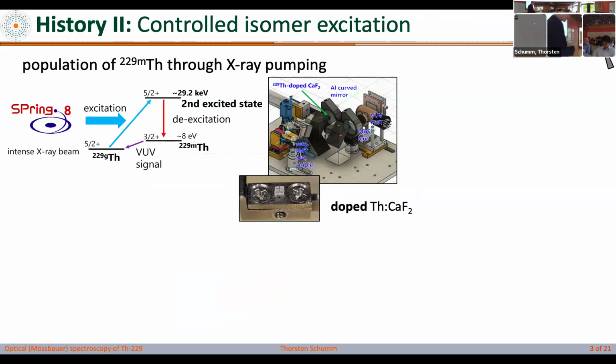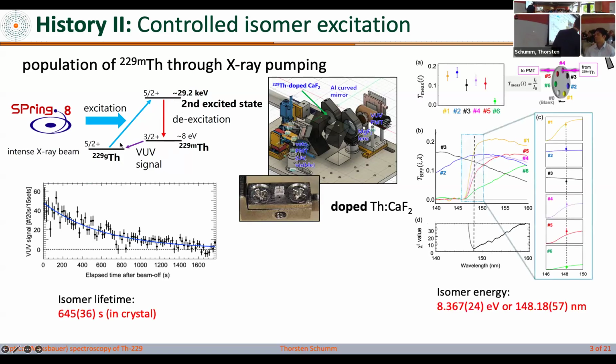We gained control in an experiment that we were performing at the SPring-8 synchrotron facility, where we excited to the second excited state using 29 keV X-ray radiation. So we essentially pump up nuclei to the second excited state. That's actually what nuclear physicists are much more familiar with, going to these high energies, and then this one spontaneously goes down very quickly. This one has an 8 picosecond lifetime. And then it goes down here, and this one lives for 10 minutes and emits the UV photon signal. So this can also be detected. And here we go. We have a decay, and we confirmed that about 10 minute lifetime.